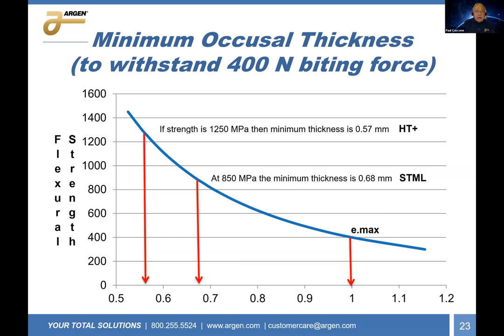Well, it's a very simple calculation. So here, in order to withstand 400 newtons, if your zirconia has a strength of 1250 megapascals, then the minimum thickness is just less than 0.6 millimeter. If, however, the zirconia is at 850, then it has to be a little thicker at 0.7. For most of the 5Y materials, we're closer to 650, and it has to be 0.8. And here, as a point of reference, you have Emax at a full millimeter, because the strength of the material is so low. So there's a direct relationship between the strength of the material and your preparation. How thick that restoration is going to be is going to determine how long it's going to last. If you get a material that has a little higher strength, you're much better off.